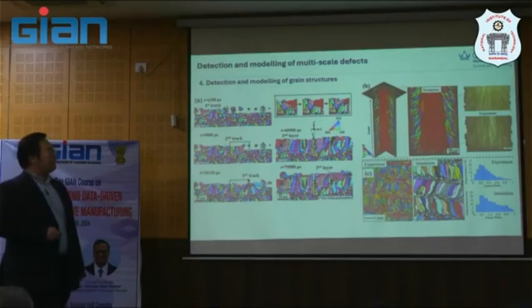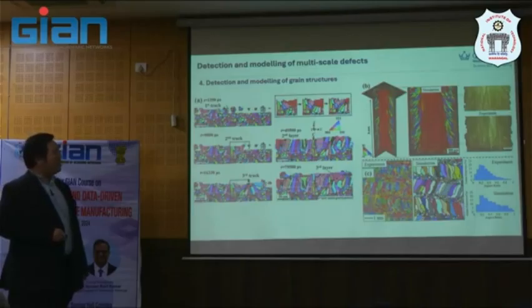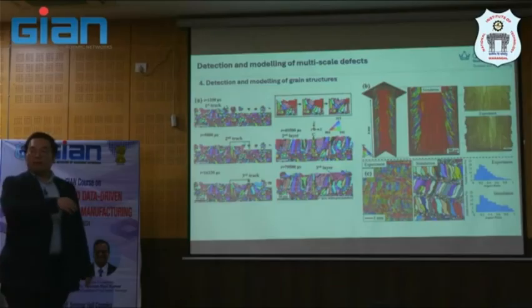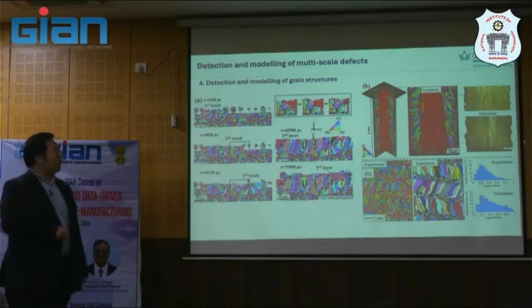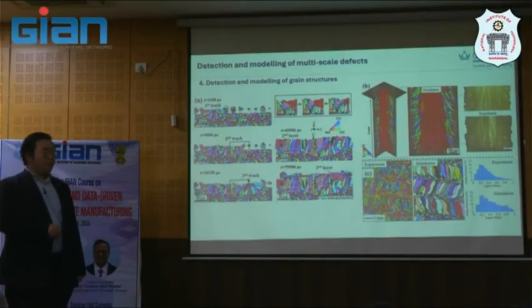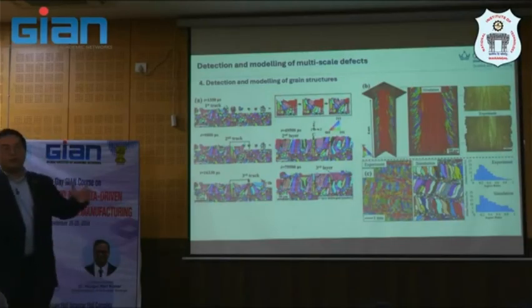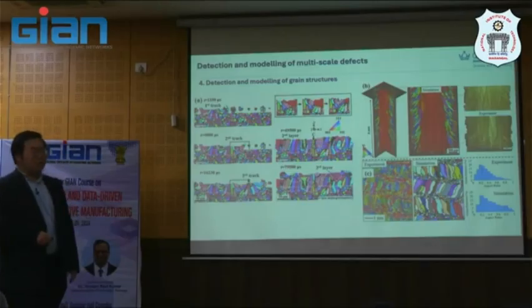microstructure that you will see at the beginning of the research in AM of metal. You will see the band of equiaxed and columnar grains here. I think this is due to the melt pool, which they did not understand very well at that time, leading to this kind of phenomenon. I mean a zigzag pattern, if you like. Some structures are very zigzag, and that's why you see quite beautiful microstructure. I'm not sure it's usable or not, but it's this beautiful structure that can be created by AM.